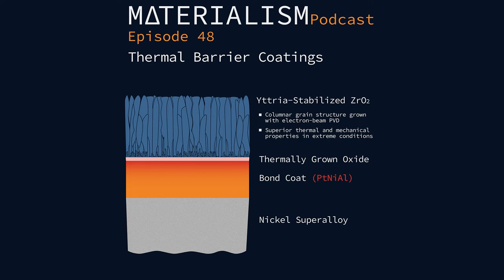This thermally grown oxide is really important. It does a couple of things. First off, it provides a barrier against future oxidation. We know this. It's a passivating layer. This is why aluminum is used in so many things. It makes a really good barrier because oxygen ions don't travel through it with ease. They have really slow diffusion. But it also serves another purpose. It helps bond the TBC, the thermal barrier coating itself, to that bond coat layer. Yeah, it's kind of like a diffusion bond, right?